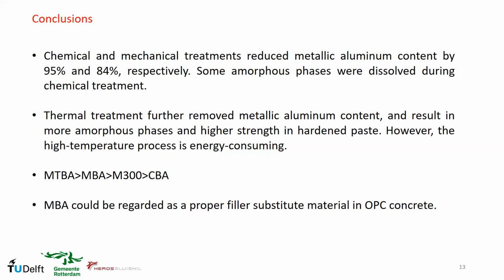Regarding the performance of substitute materials, MTBA is better than MBA, then the micro sand, and the chemically treated bottom ash is the worst. And finally, MBA could be regarded as a proper filler substitute material in OPC concrete.